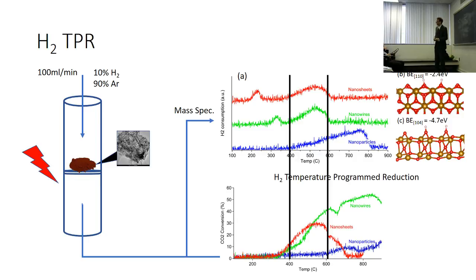The question of crystal facet was one we had before. Is the nanoparticle worse because it's worse at absorbing hydrogen on the surface? We had people in Victor Batista's group again model some iron oxide, and what they modeled was the 104 facet versus the 110.